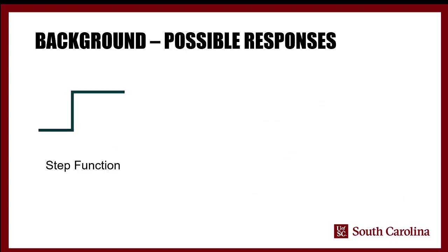So there's really 3 possible responses depending on what you're doing. First, you could have a step function, which means that a particle hits and sticks and continuously increases the amount of current that is passing, meaning that it's catalyzing a reaction, and that just continues. You can have a step decay function, which can mean a couple of different things.